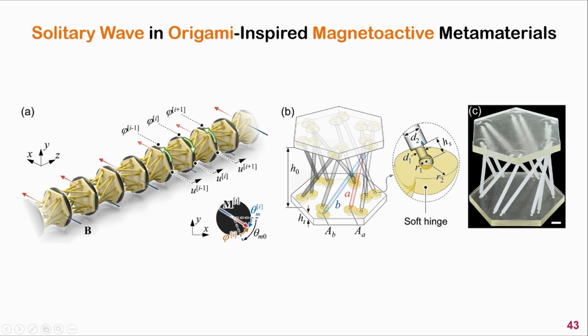Okay, in addition to the rotating square metamaterial system, we also investigated solitary waves in an origami-inspired magnetoactive metamaterial system. As shown here, the unit cell structure of the system consists of 2 plates and 12 beams. More importantly, the beam and the plate are connected via a highly deformable hinge that is made of very soft materials. Experimentally, the whole unit cell structure can be fabricated using multi-material 3D printing technique.